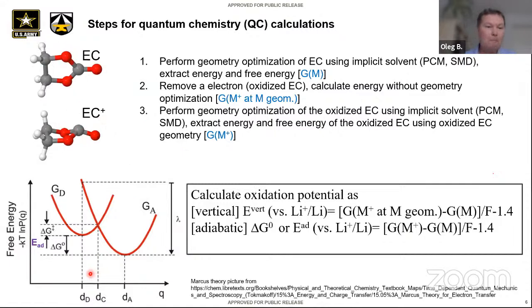In the sense of Marcus electron transfer theory, we have acceptor and donor states. In this case, the minima of both states give this E adiabatic, and if we do not relax geometries, then it will be the vertical oxidation, which is related to lambda and can be used to understand kinetics. So that's going to be my connection with the kinetics.